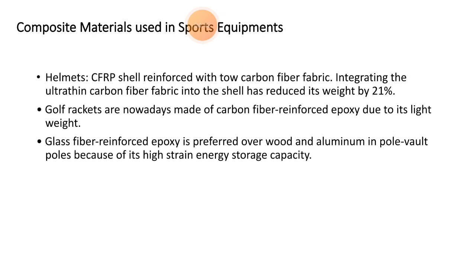Helmets use a CFRP shell reinforced with tow carbon fibre fabric. Integrating ultra-thin carbon fibre fabrics into the shell has reduced its weight by 21%. Golf clubs are nowadays made of carbon fibre in epoxy resin due to their light weight. Glass fibre in epoxy resin is preferred over wood and aluminum in pole vault applications because of its high strain energy storage capacity.